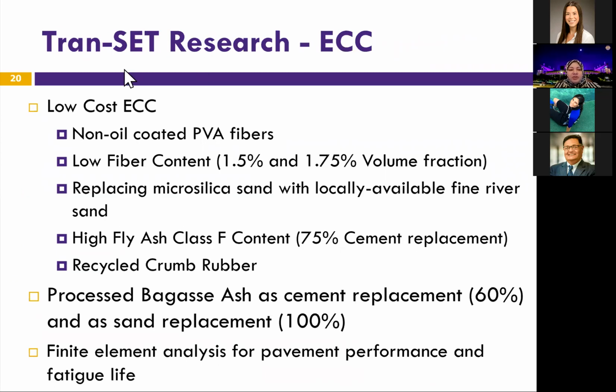So we focused on a number of things, developing low-cost ECCs. We started testing or developing mixes that can work with non-coated PVA fibers to reduce the cost of the fiber. We also reduced the fiber volume fraction from 2 to 1.5 and 1.75, and we got that to work. Another ingredient that's expensive in ECC is microsilica sand. It has to be very round, very soft, very small, fine sand. So we replaced the microsilica sand with locally available materials that are present in Louisiana and in Region 6. And we started replacing some of the cement content with High Fly Ash Class F content. And we also experimented with using recycled content from crumb rubber.